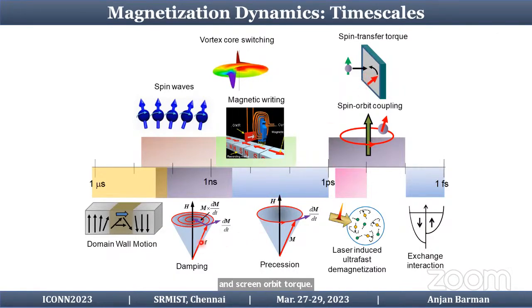Then magnetization precession and damping fall in this picosecond to nanosecond time scale, where magnetic writing, vortex core switching, and spin wave take place. And the slower dynamics is the domain wall dynamics, which is actually the core of present data storage technology, which falls in the microsecond to millisecond time scale. So the ultrafast demagnetization is the fastest phenomenon which occurs in the femtosecond or 10 to the minus 15 second.